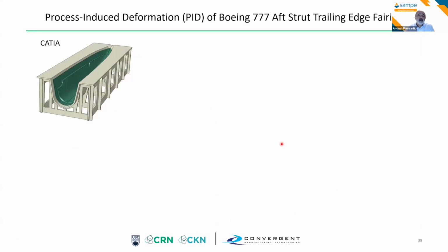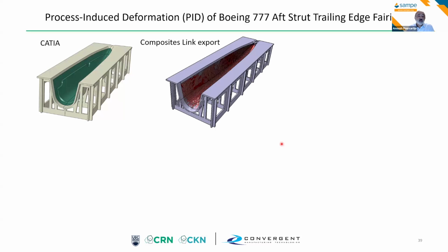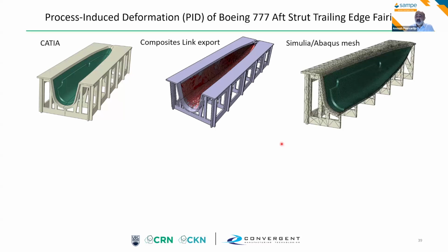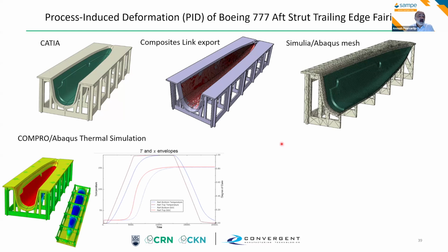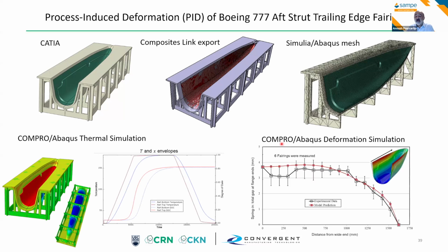Again, there's always exceptions, but on average, what we're looking at here is the 777 aft strut trailing edge fairing, and you can take a CAD model, export it, mesh it, then do a thermal simulation to make sure that the thermal history is correct, and then run a PID simulation, and you can see that the PID simulation does a great job of predicting the springing of this structure.